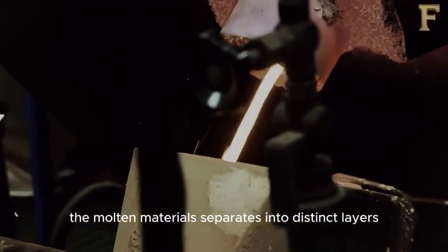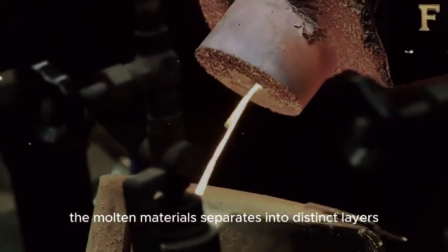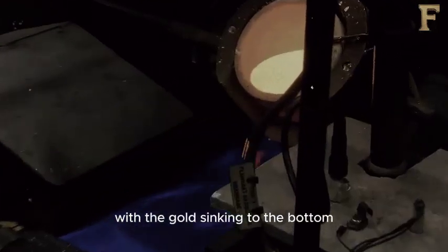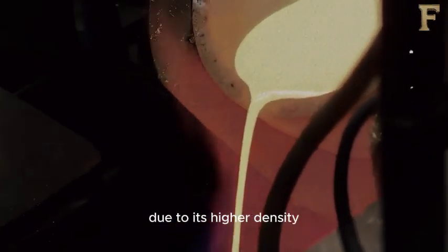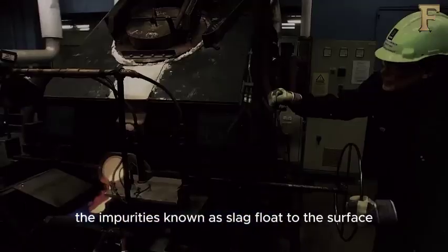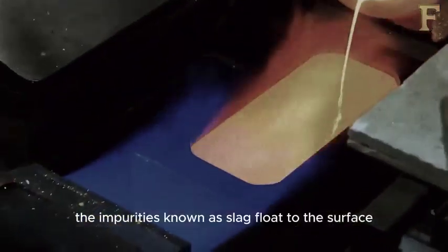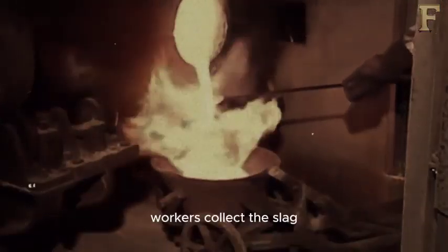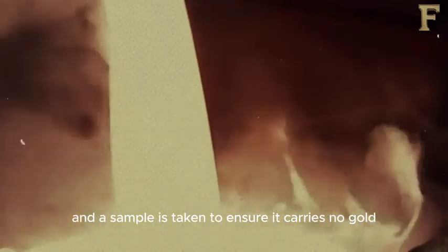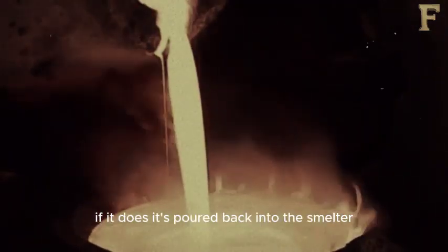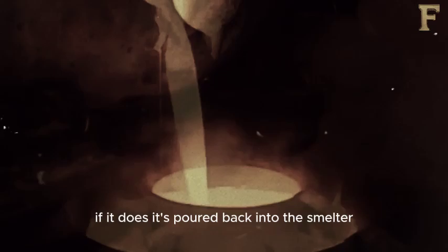The molten material separates into distinct layers based on their densities, with the gold sinking to the bottom due to its higher density. The impurities, known as slag, float to the surface. Workers collect the slag, and a sample is taken to ensure it carries no gold. If it does, it's poured back into the smelter until it is completely gold-free.